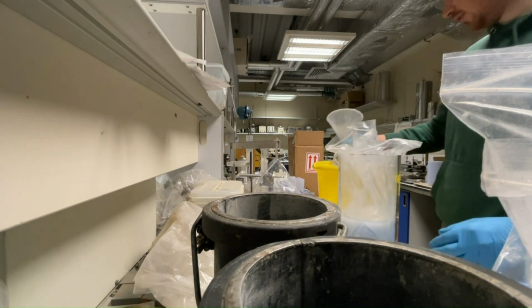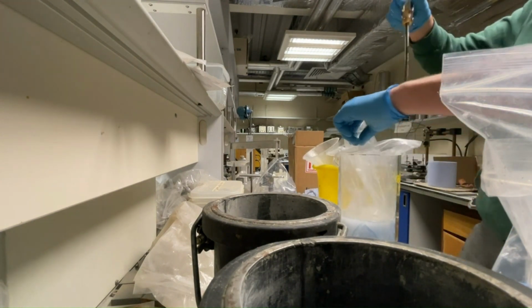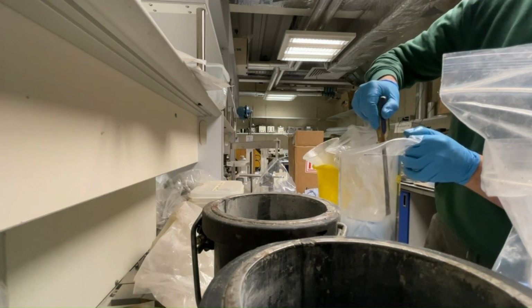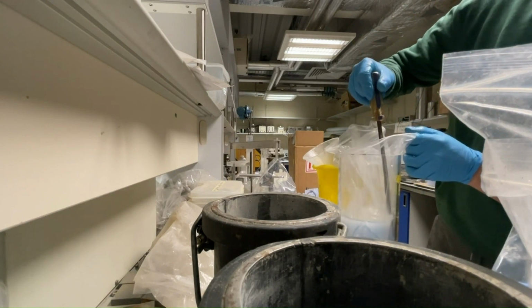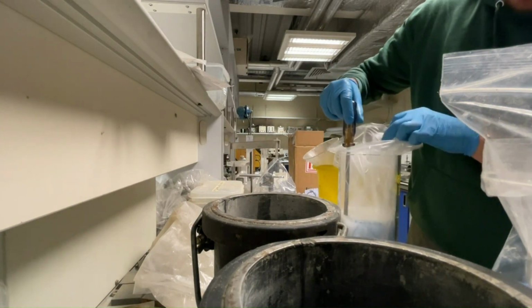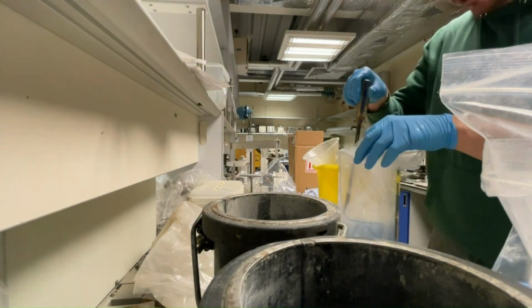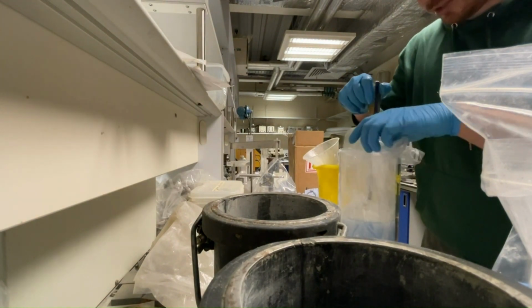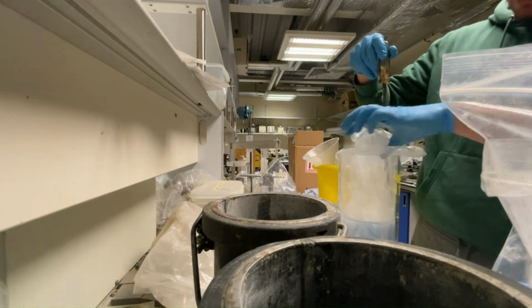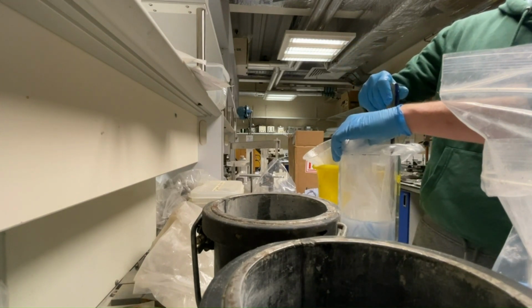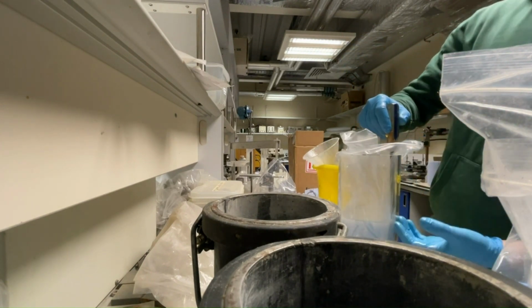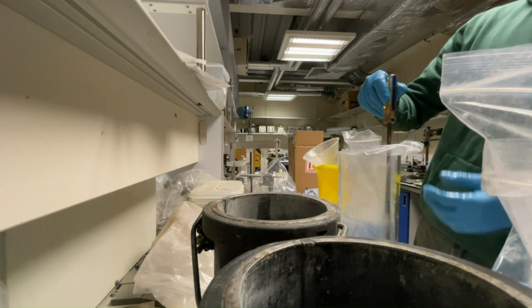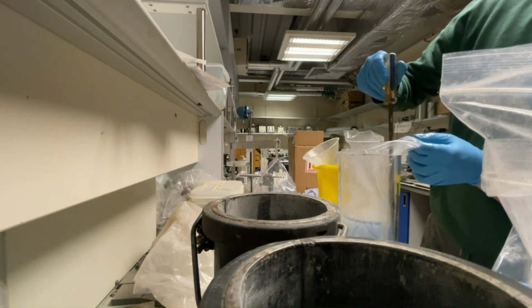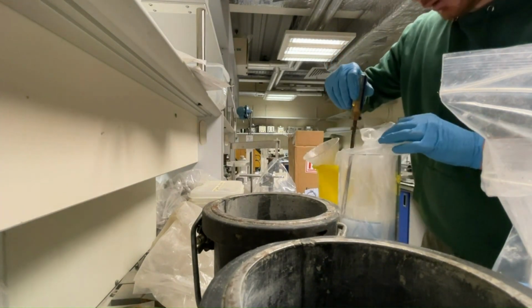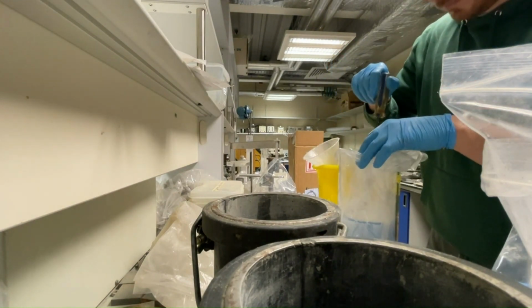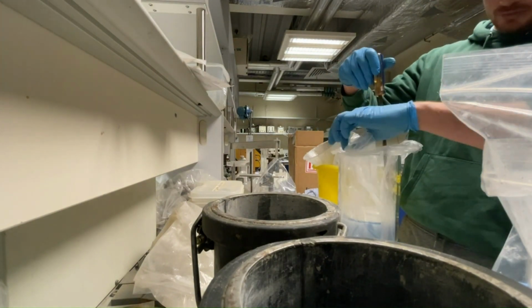So at this point, I'm just going to take the screwdriver, which we've been using, and just gently move the resin around the bag. Be careful not to pinch the bag, because you can quite easily tear it, and when you tear it, the resin will rest against the Perspex, and it will make it a lot more difficult to move your sample around once it's cured. Obviously we'll need to raise the samples up to the top to put the plastic pucks in and the base coupler. So just make sure to avoid popping the bag. Done this a couple of times, makes things very difficult, time consuming.